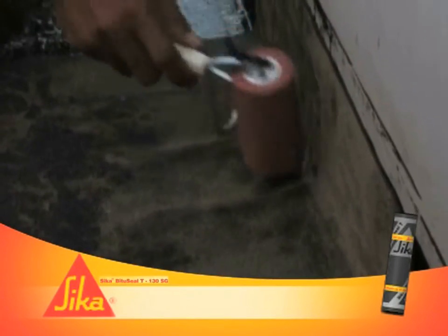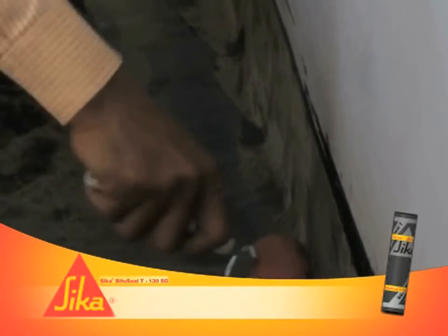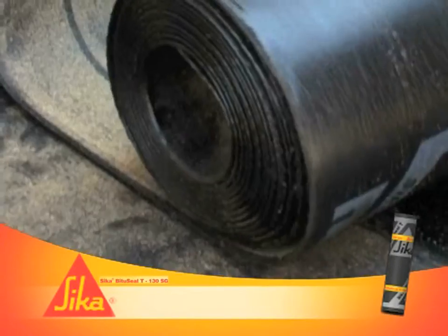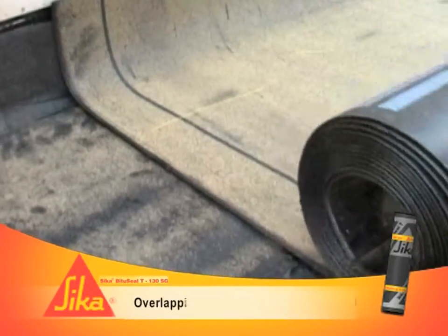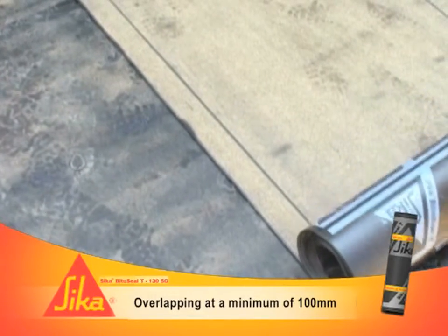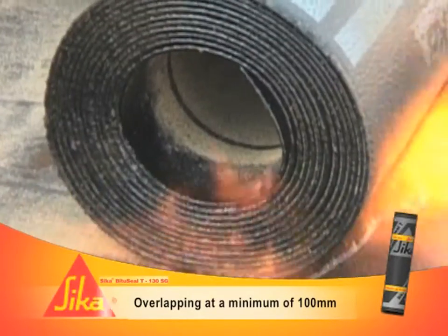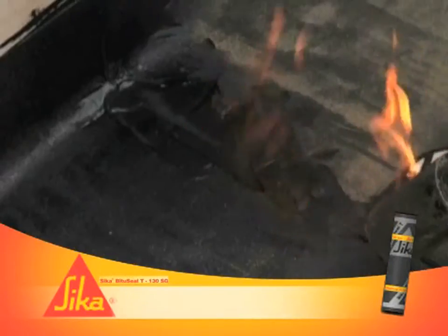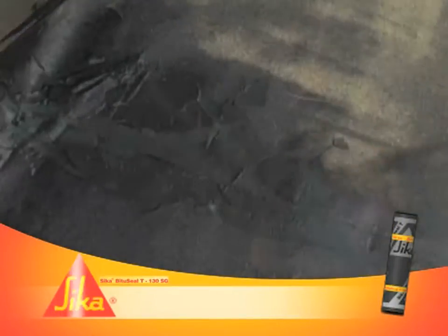The torched-on membrane must be firmly pressed onto the substrate to avoid air entrapment. All membranes must be overlapped with a minimum of 100 millimeters. For roof areas, protect the surface with boards of 2 to 3 centimeters.